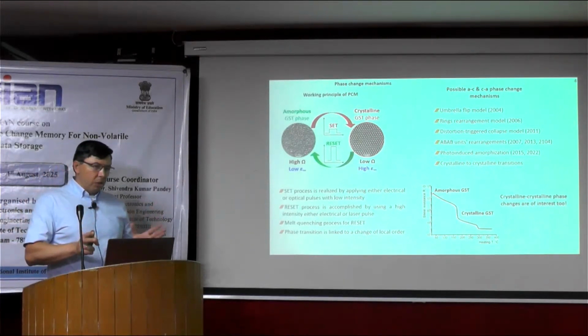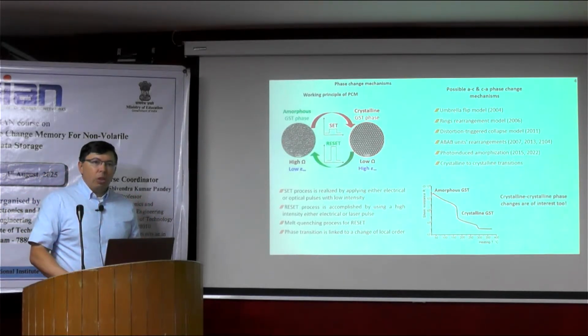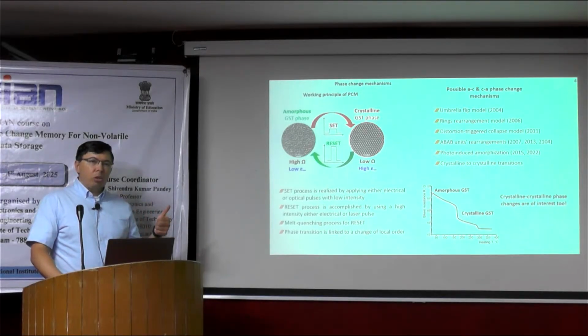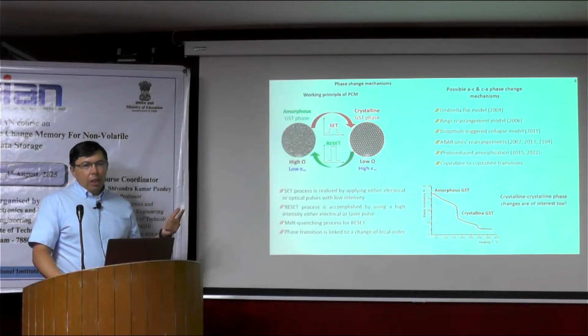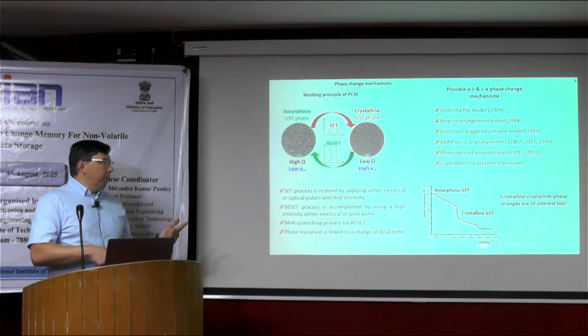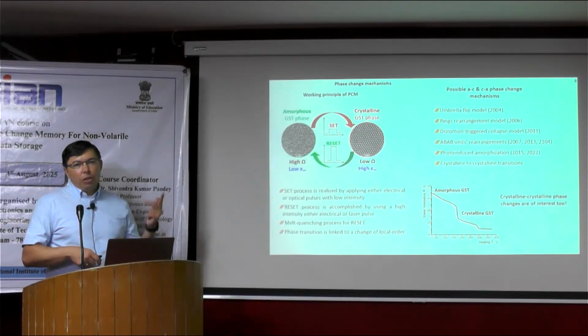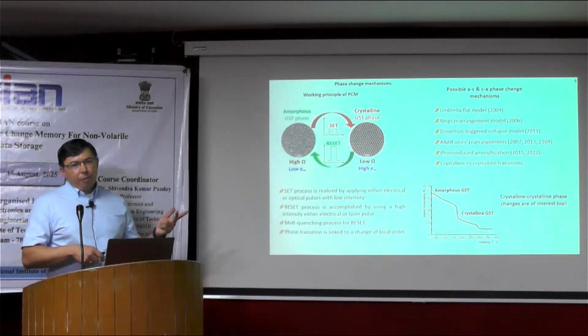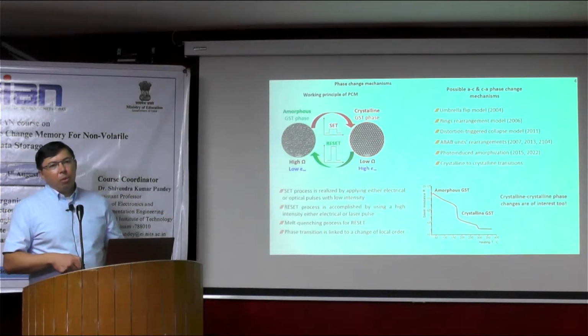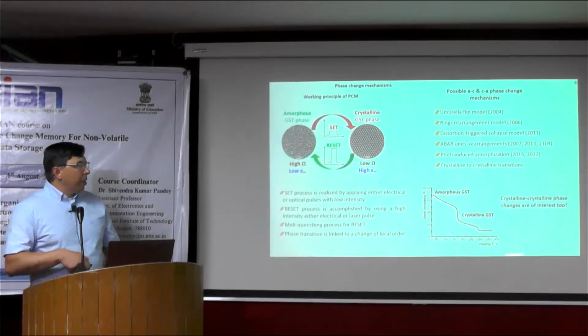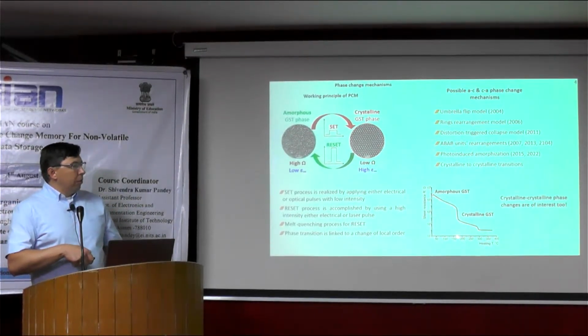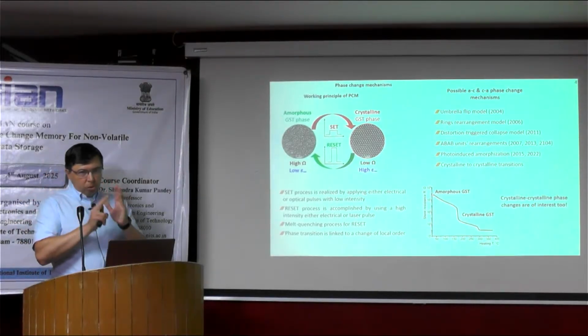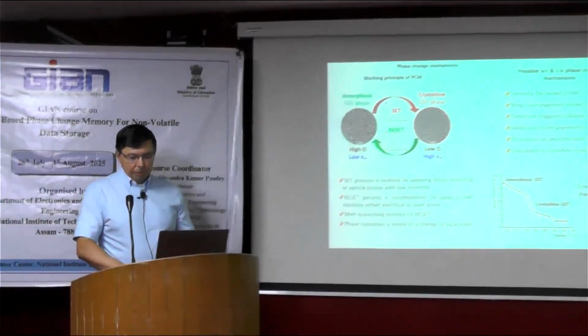Mixture. But for vacancy ordered, there is a window. You have to identify it for your system, because it's compositional dependent and also thickness dependent. And it's also heating rate dependent, how fast you heat your system. Because I think some data shows if you heat it very fast, you can overcome this window, with a very short one. Short. Yeah. Okay. Thank you.